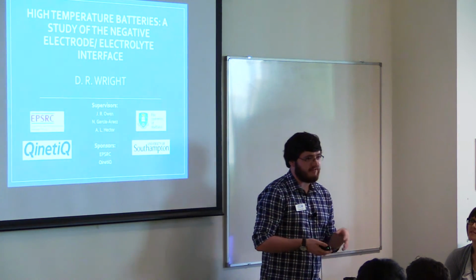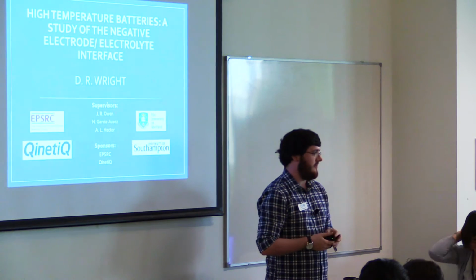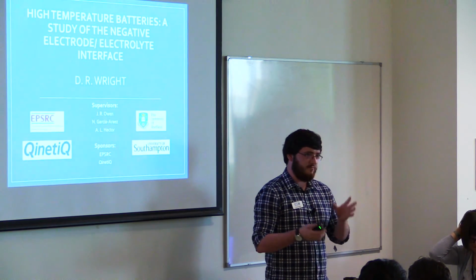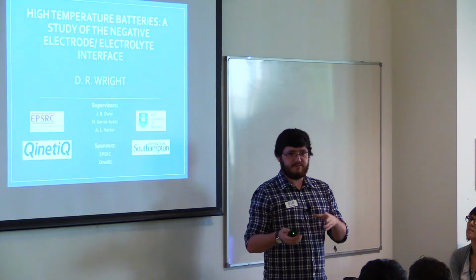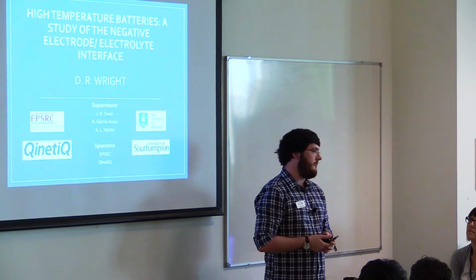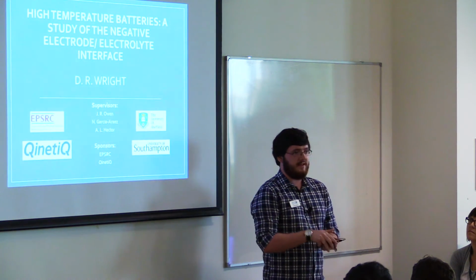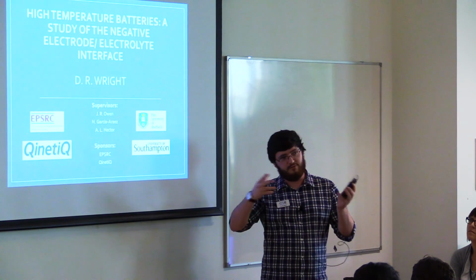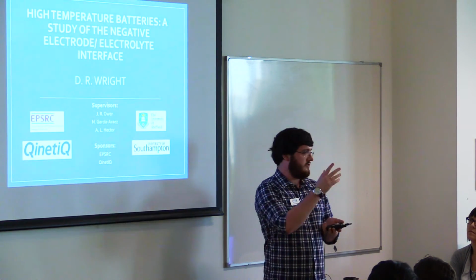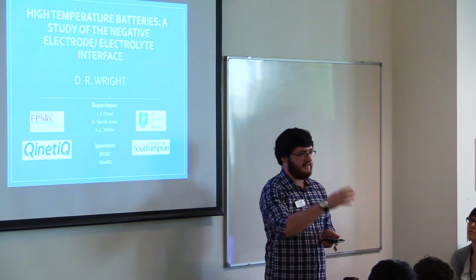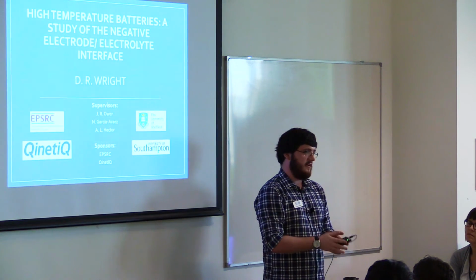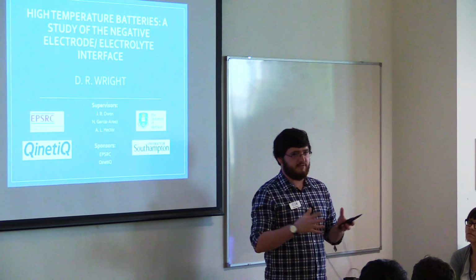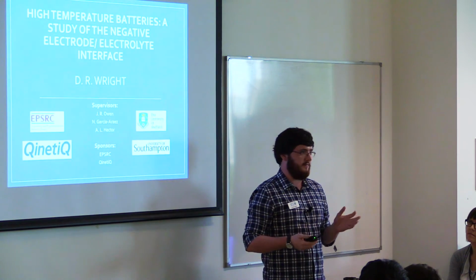I will be doing a lot of microscopy during this project. So SEM, TEM, but equally we've got this new module, liquid cell attachments we can attach to the TEM, and I'll hopefully be able to observe the lithium intercalation into the silicon structure and record it in the TEM. Obviously you can't see the lithium, but I'll hopefully be able to see the silicon structure expand and contract, which will evidence the lithium entering into it.